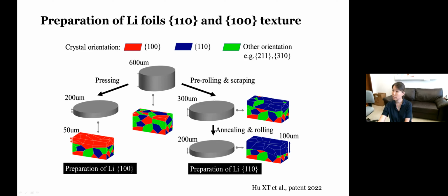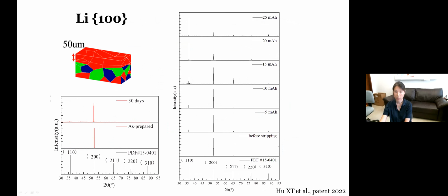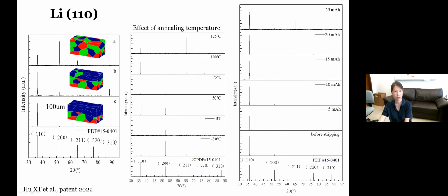The preparation process takes two steps. The first step, following the theory, is just to use the shear stress and create a certain amount of shear texturing in the sample. So we did. By pre-rolling and scraping the sample, we're able to get some of the shear texture grains in the lithium foils. And after that, we need the recrystallization process to get the dominance of the lithium 110, right? And that we did. And here are the results, right?